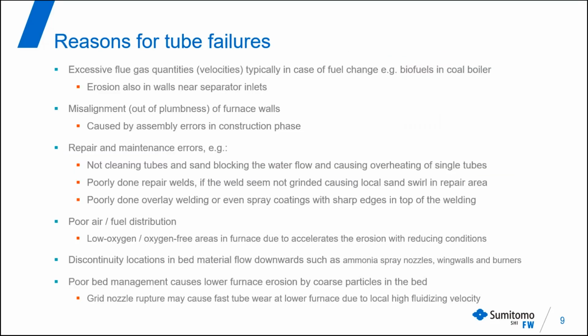Here we have collected most typical reasons for tube failures in CFB boiler furnace walls, which is always related to erosion or corrosion, or sometimes even those working together so that the wastage can be even faster. Erosion is typically caused by too high velocities in the furnace. This is related maybe to overloading the boiler or changing the fuel that contributes to have more flue gases than the original fuel.